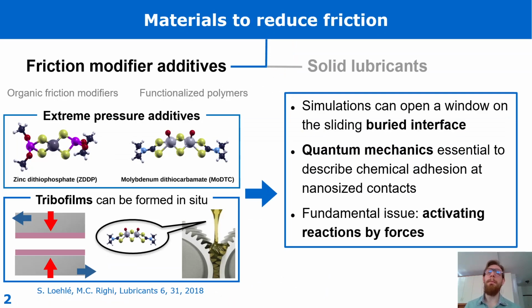The materials typically employed to reduce friction can be divided into friction modifier additives that are introduced in liquid media and solid lubricants that operate in dry conditions. I am particularly interested in extreme pressure additives. They are complexes such as ZDDP or MoDTC that contain elements, sulfur and phosphorus for example, able to passivate the sliding part. In fact, when these complexes are in tribological conditions, they can break down and release elements or molecular fragments that can passivate the metallic substrate or recombine into tribofilms.